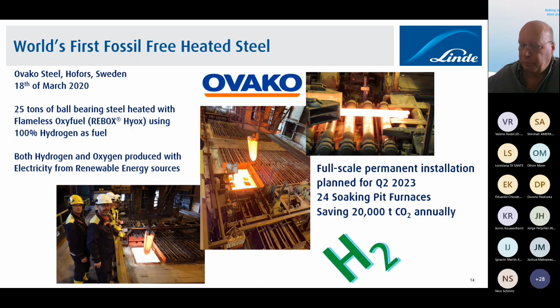This has been tested in full scale, and one great example is the steel producer Ovako, based in Sweden, where we 2.5 years ago did the first full-scale test. We have done other full-scale tests together with other customers over time. And that has been done for heating of steel. So we have done tests with, in this case, 25 tons of ball bearing steel grades. We have done tests with stainless steel up to 50 ton, etc.